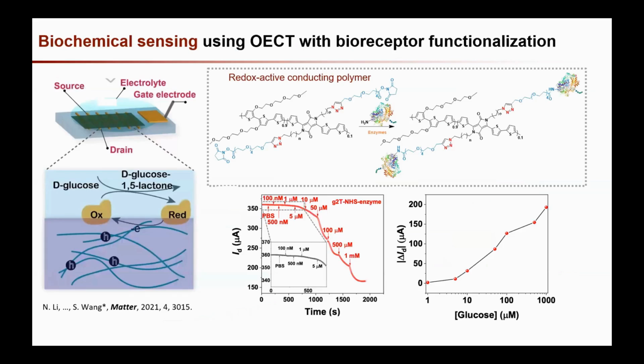One example that we have shown this is from the work that we utilize this semiconducting polymer, redox active conducting polymer as a channel layer. And by functionalizing the side chain of the semiconducting polymer covalently with the protein, the enzyme for glucose, just directly functionalize onto the side chain. Then when we use this semiconducting polymer as a channel layer in the so-called OECT, it can have the high sensitivity and the specific sensing function for the presence of the glucose. So as you can see from this performance.